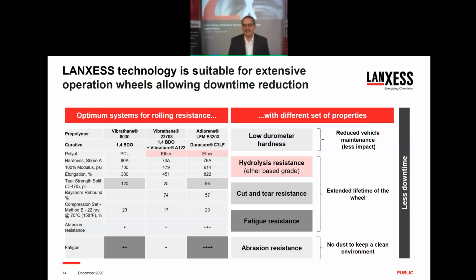Over on the right-hand side is the Adiprene LFM E320. So again, that's an ether, but it's a newly designed ether, which provides a higher tear strength. So it bridges that gap. It's over 3 times more tear strength than the conventional ether. It's the best out of all 3 of the materials in terms of fatigue. Actually, the LFMs have best-in-class fatigue strength and phenomenal abrasion resistance. So what we have here is 3 different solutions that provide low rolling resistance, but they all have their differences in terms of pros and cons, whereas the LFM combines those 2 and bridges that gap a little bit between the ester or the polycaprolactone and the ether.